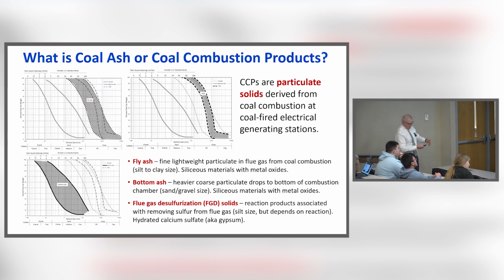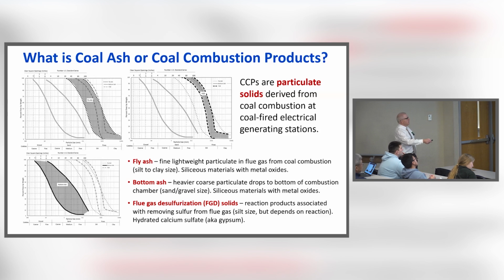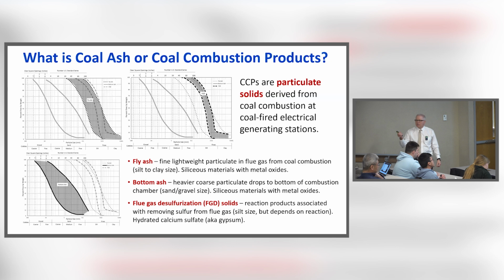That's this stuff up here in the left, and this is a particle size curve. So those of you who have been in your geotechnical courses, this is percent finer, and this is particle size. And the fly ashes are in the silt, fine sand, but predominantly silt size all the way over to the clay. But they're typically very fine, powdery type materials in the silt size particle range.